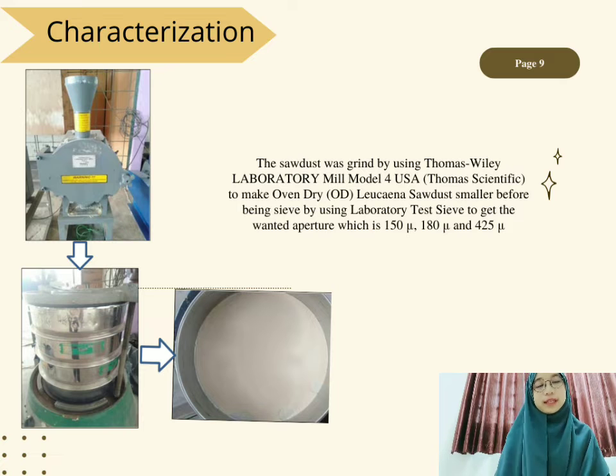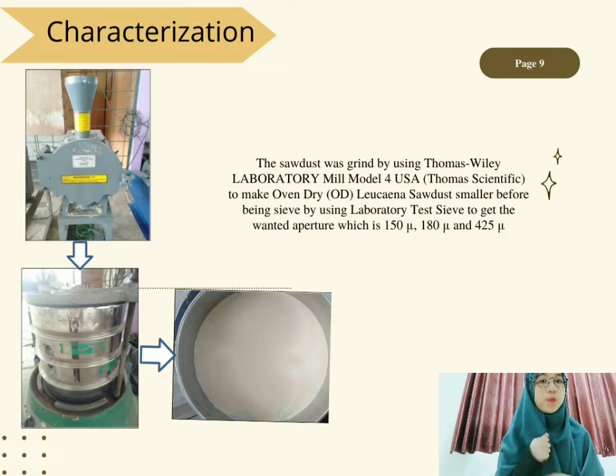The sawdust was then ground by using a Thomas Wiley laboratory mill model from Thomas Scientific, USA, as we want to make the oven-dried Leucaena sawdust smaller before being sieved by a laboratory sieve, as we want to get the wanted aperture, which is the size of 180 micrometer, 150 micrometer, and also 425 micrometer.